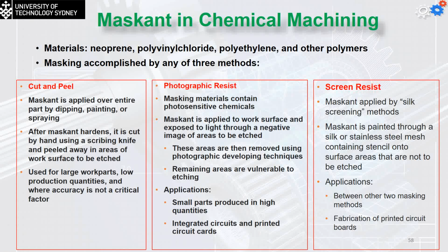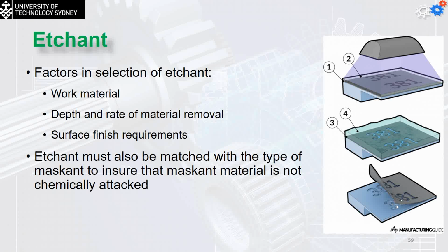For the etching material, the factor of selection is what reacts with what. Depending on the work material you're going to use, you choose the etching material for that. Also, some acids or alkalines have a higher reaction with certain work materials, and this will decide the depth and the rate of material removal. Finally, what are the surface finishing requirements? Some etching materials give a very bad surface finish, while others give a very fine surface finish. The etchant also must be matched with the type of maskant to ensure that the maskant material is not chemically attacked. So you have to check whether it's going to affect the masking material or not.